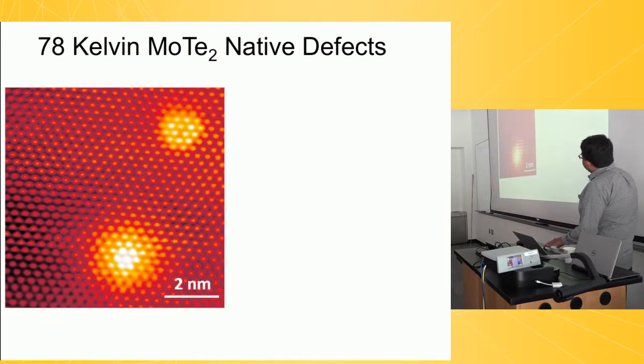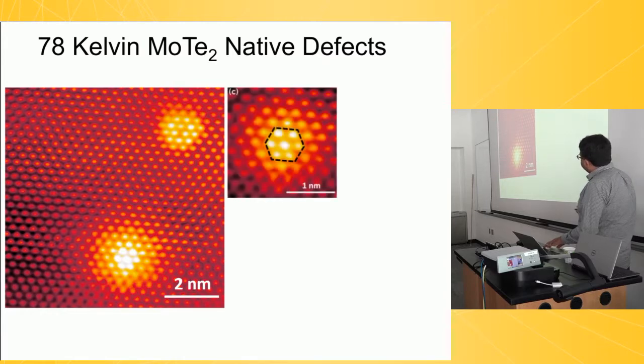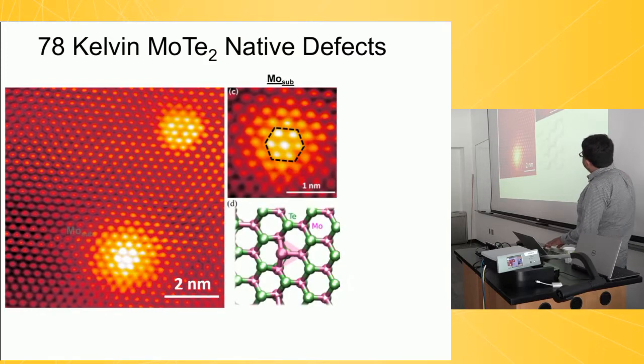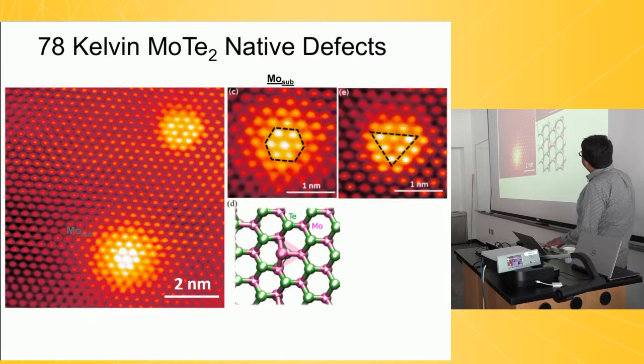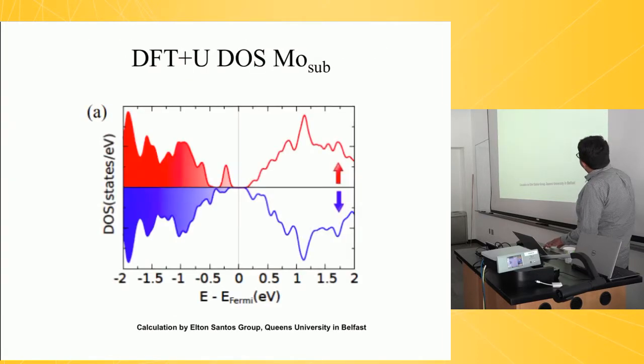These are the same two types of defects, the metal vacancy and the chalcogen antisite. If you look at the chalcogen antisite, and you measure carefully the spectrum on the chalcogen antisite for molybdenum ditelluride, let me jump straight to this. Oh, OK. So I had my story upside down.